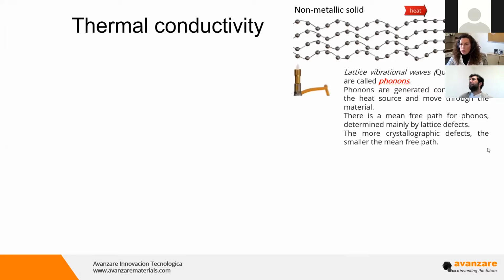I want to explain that in a non-metallic solid, as in the case of graphene, the heat is moved from the hot part to the cold part thanks to the vibrational waves in the lattice. This movement is made by quasiparticles, which are called phonons. These phonons are continuously generated at the hot part and transported to the cold part. The movement of these phonons is usually determined by the crystallographic defects. And as we will see after, it's really important in the case of graphene.